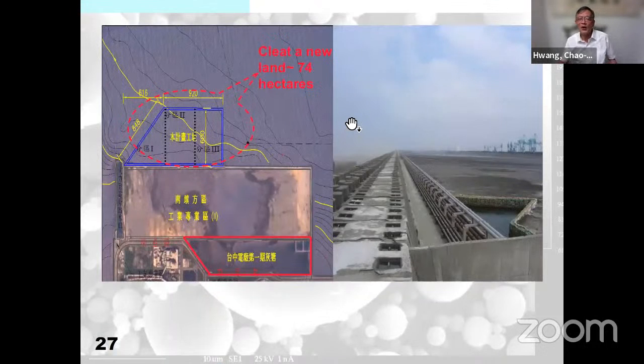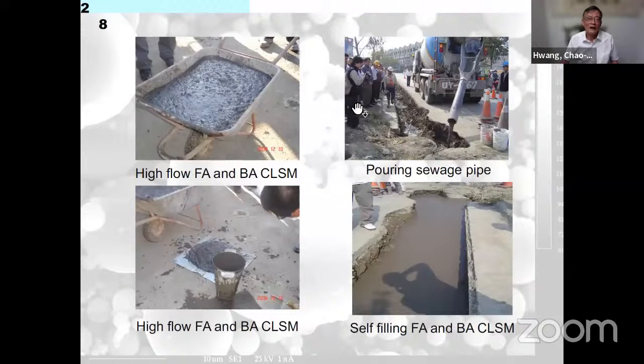And this one is in Taichung, in Zhanghua, actually, for the ash pond. So we use bottom ash and fly ash, and we use a controlled low strength material. And they save a lot of money, a lot of money. Next, please. So this high flowing fly ash and bottom ash controlled low strength material, in Taiwan now, we have a label as a green material because it saves at least 50 to 60% of cement. So the concrete, flowing like this one, can fill the pipe. And this is a very common use in Taiwan. Next, please.